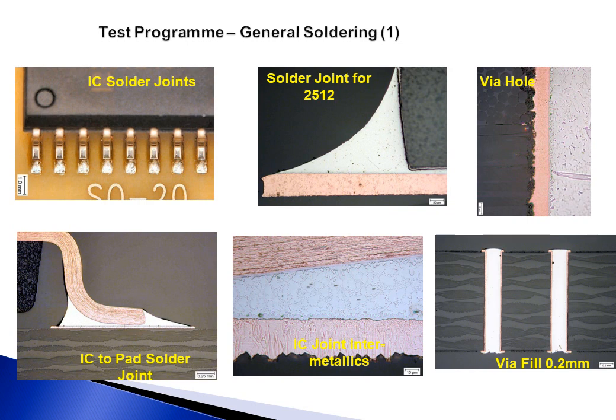Tried soldering vias and got quite good results from that, and you can see the intermetallics of the via. I managed to solder vias at 0.2 millimeter and got the solder right up to the top. It's not quite over the top. I couldn't manage to get it to put a fillet on the top, but it came pretty close and certainly met the IPC 610 standards. There's a better view of the joint where you can see the intermetallics, which are quite clean and quite good.